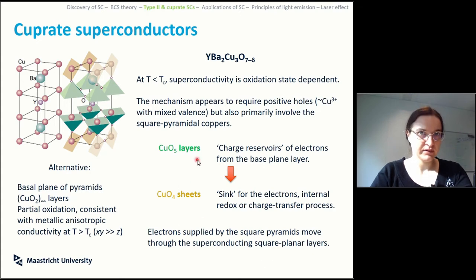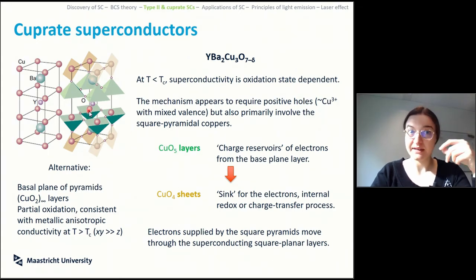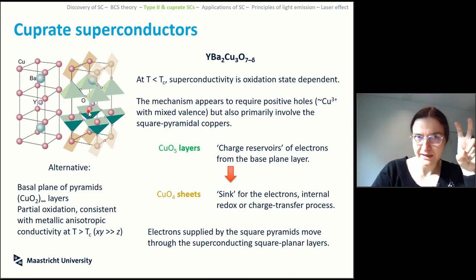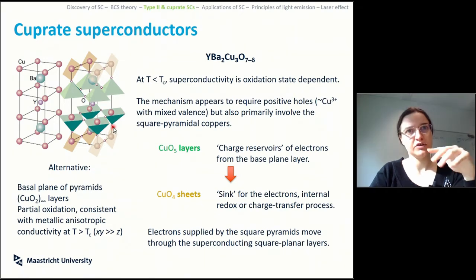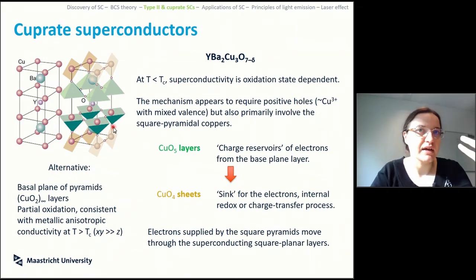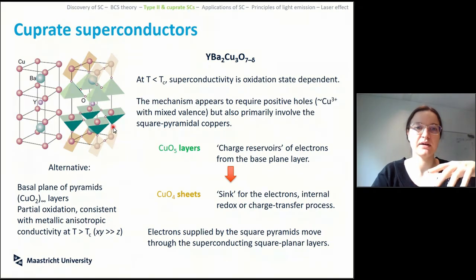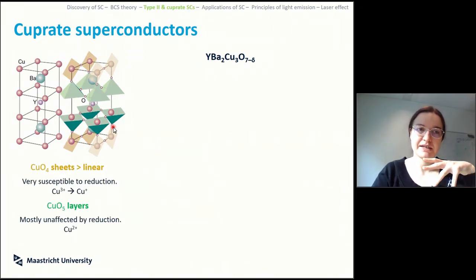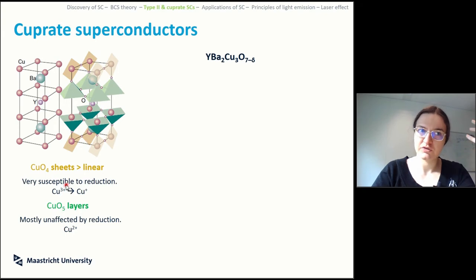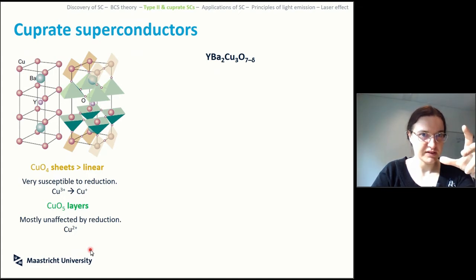So the electrons are supplied by this square pyramid thing that has oxidation state copper 2 plus, and the sheets over here that have an oxidation state copper 3 plus are the ones that can actually be reduced if you manage to bring the electrons around. Now, this thing is incredibly susceptible to reduction, so copper 3 all over the place, and this thing should be mostly unaffected by reduction. But given that you want to tweak the oxidation states, if the oxidation state is not what you expect and not averaged in the way you expect, your material might very well not behave in the way you think.